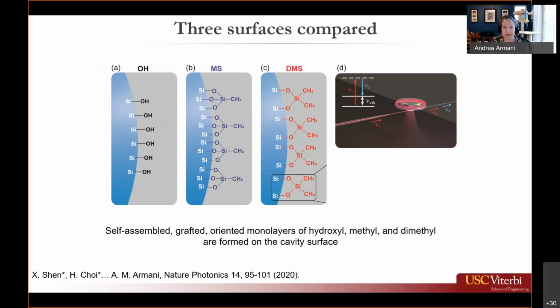So we tried two different surface chemistries in addition to the primary surface. On a normal silica device, your surface has hydroxyl groups on it, which are just OH bonds. Now, if you nanostructure the surface by doing a very simple surface chemistry called a silanization reaction, we can create a very structured Si-O-Si bond. And we looked at two different surfaces. In the first one, we had an Si-O-Si bond that then had a second methyl group on there. And in the second surface chemistry we looked at, we added two methyl bonds to that Si-O-Si bond. And these are covalent surface chemistries, so they're permanently anchored to the surface.